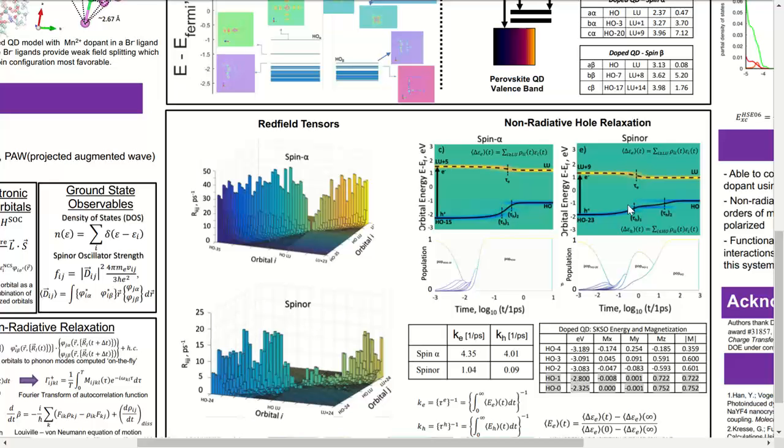I didn't exactly figure out the physical reasoning behind this, because with spinors you can't really compute orbitals, so you can't compare orbitals from the spin alpha with orbitals from the spinor. But I would suspect that spin orbit coupling tends to shrink your orbitals due to faster motion. It contracts your orbitals. So if your orbitals are more contracted, there's going to be less spatial overlap for it to be non-orthogonal with it. That's the best idea I have at the moment.